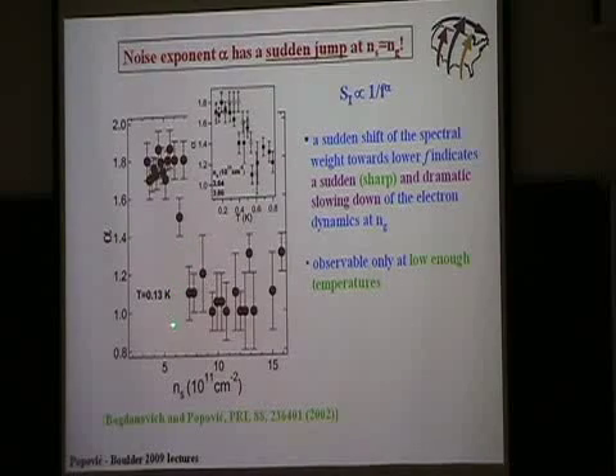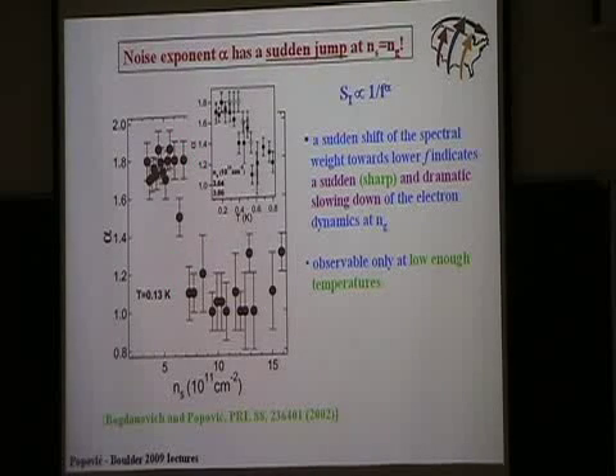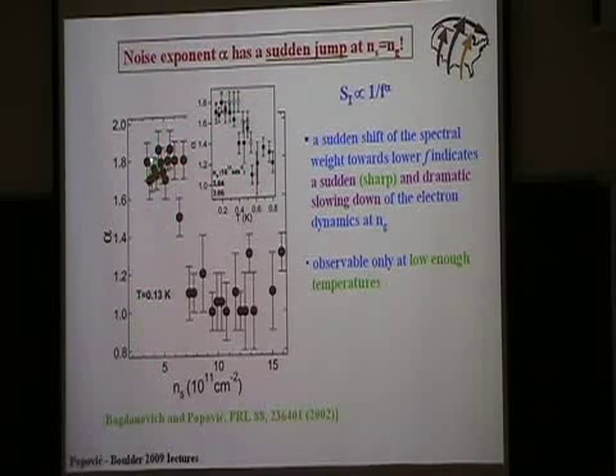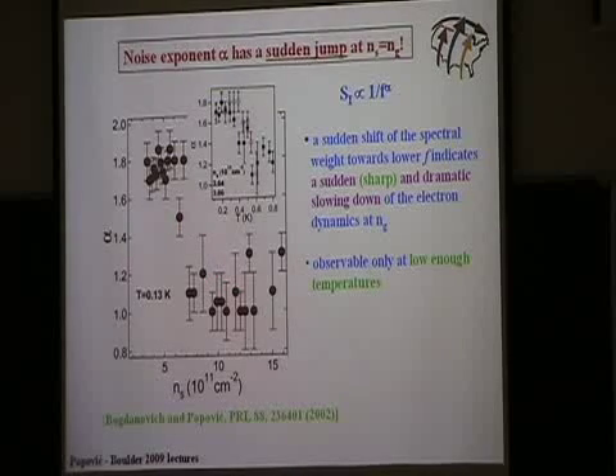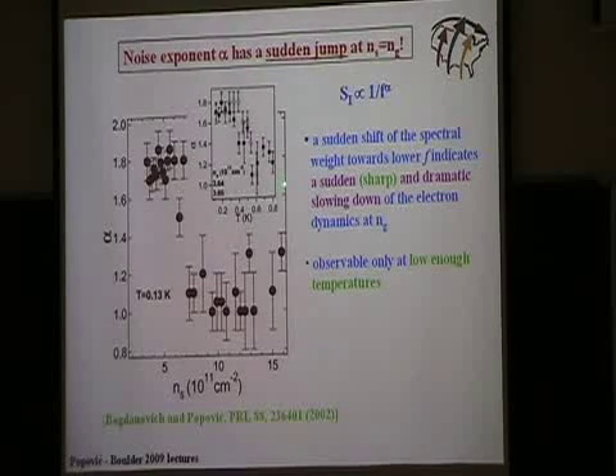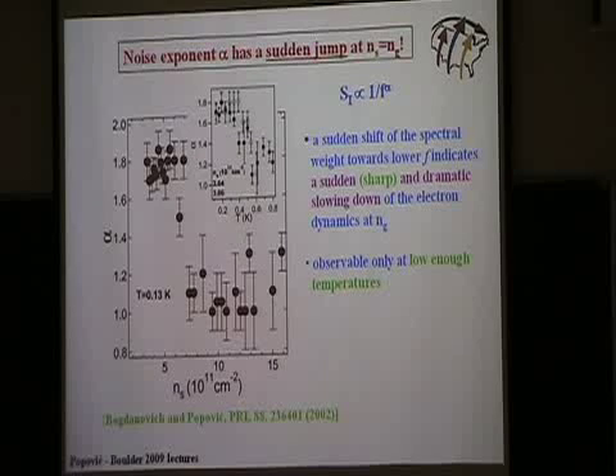So this behavior is very sharp, and this was, I think, much better evidence for the glass transition. It's sharper than those relaxation curves. I mean, this is much more dramatic. The inset shows the temperature dependence of this alpha. For example, if you fix the density here and you raise the temperature, it gradually decreases. So this transition is no longer very sharp. This behavior as a function of temperature is very gradual. So to us, this seems to indicate that the glass transition really takes place at zero temperature, because there is nothing dramatic happening at any temperature, and this was later confirmed with the measurements of the relaxation and equilibration times.